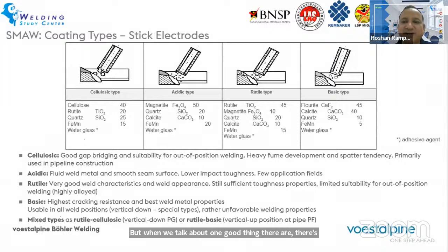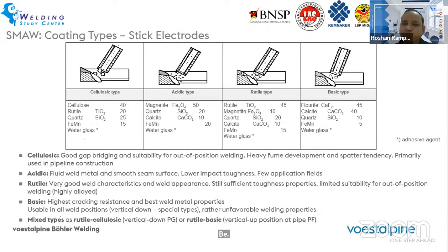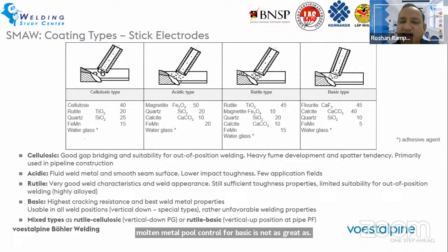But when we talk about one good thing, there's a trade-off with another property. So basic type of electrode gives us much better mechanical properties, specifically impact property, but the negative side is the welding behavior. The molten metal pool control for basic is not as great as rutile type. The slag detachability is not so good for basic type, whereas for rutile type, the slag is easily removable. For basic type, you need to do some grinding or maybe use a hammer to remove the slag.